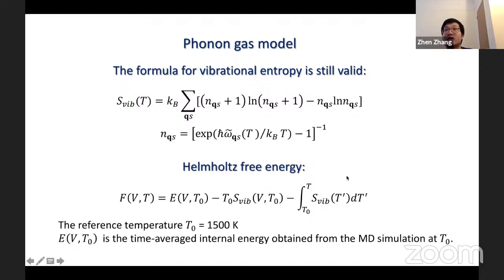Since the phonon quasi-particles are only well-defined at high temperature, a reference temperature T0 equals 1500 Kelvin was chosen as the integral lower bound. The reference DFT energy is the time averaged internal energy obtained from the MD simulations at T0. Then we integrate the entropy to obtain the free energies at temperatures above T0. From the free energy, all the thermodynamic properties can be obtained.